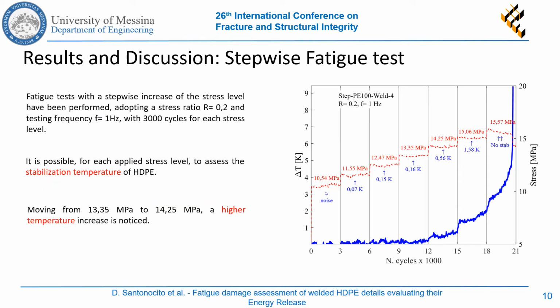Fatigue tests with a stepwise increase of the applied stress level have been performed on two specimens with a stress ratio of 0.2 and 1 Hz of frequency. During the test, the superficial temperature has been monitored with the infrared camera. For each stress level, it is possible to observe and estimate a stabilization temperature. In particular, for stress levels below 14 MPa, we observe none to very small temperature increment compared to the first cycle temperature. As the applied stress is greater than 14 MPa, it is possible to observe higher stabilization temperature. For the last stress level, no stabilization has been reached and the temperature increases until the specimen failure.